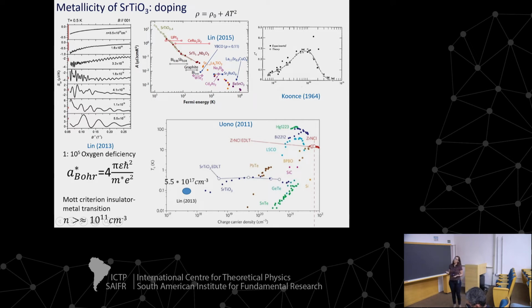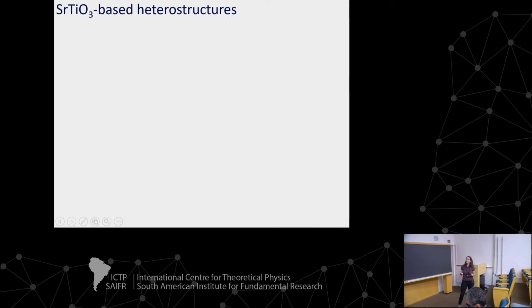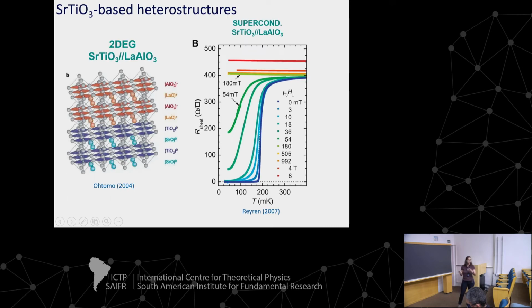So at this point, in historic order, I want to mention, I will not speak about heterostructures, but actually STO became interesting again because of the discovery of heterostructures. We know that at the interface, and it's already almost 20 years since this work, we can see a metallic interface when we face two different insulating perovskites. We can even observe superconductivity.